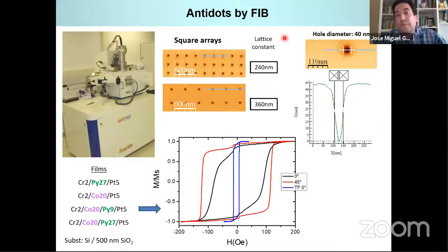In the case of the antidotes by focused ion beam, the idea is that we can drill the nanoholes with a periodicity that cannot be achieved, for instance, using the alumina template method that is used by other groups. So for instance, we can have square arrays of nanoholes. You can see that we have prepared arrays with different periodicity, 240 or 360 nanometers. And the films are made of permalloy, cobalt, or bilayer films with cobalt or permalloy. The initial thin film is the one that exhibits the loop in blue. And by drilling the holes, the sample hardens a lot. The coercivity increases because these holes, as you will see in a minute, change the domain state of the sample.